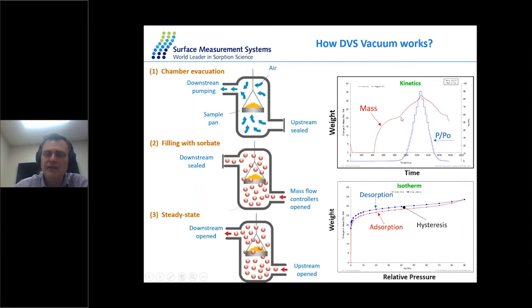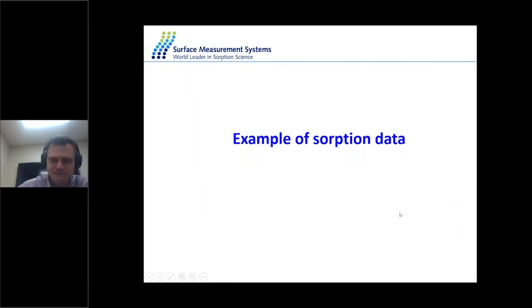From these mass equilibrium points at the different partial pressures, we then calculate the isotherm. In the plot here, we have adsorption and desorption isotherms at 25 degrees. On the x-axis you have the partial pressure, P over P naught, where P is the pressure and P naught is the saturation pressure of the solvent. On the left-hand side you have the weight. Here we represent a change in mass, but this can be converted to moles per gram. Adsorption is in red, desorption in blue, and the small gap is called hysteresis.